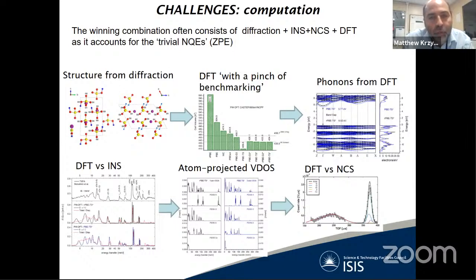In terms of challenges for further development of the technique and computation centered around this, let me start by stating that very often one of the winning combinations in terms of benchmarking of experimental results with theoretical predictions is a combination whereby we consistently try to fit globally diffraction, inelastic neutron scattering, and neutron Compton scattering data to DFT predictions. And those DFT predictions sometimes even suffice to be at the level of lattice dynamics, especially for heavier nuclei. And this allows us to characterize roughly the system. This is the starting point for any further consideration in terms of modeling of zero point energies and other nuclear quantum effects. This is usually where we start from. This is sometimes where we are also successful, where we can already draw conclusions.